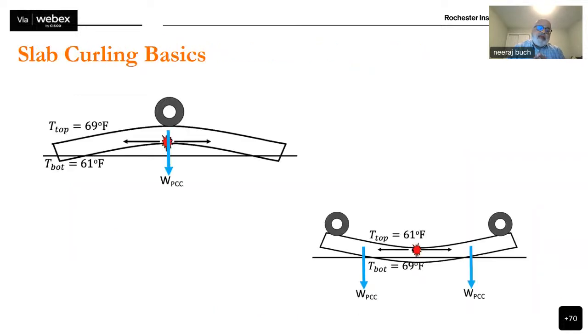So the falling weight deflectometer measurements do get impacted by the geometric deformation of a concrete slab. What I mean by that is that during the daytime, the surface of the slab is hot and the bottom of the slab is not as hot. When that happens, the slab is positively curled because there is a positive temperature gradient in the concrete slab. This little cartoon is telling you that the surface temperature is hotter than the underside of the slab. When that happens, the skin of the slab expands and you get this positive gradient, which is called positive curling of the concrete slab.